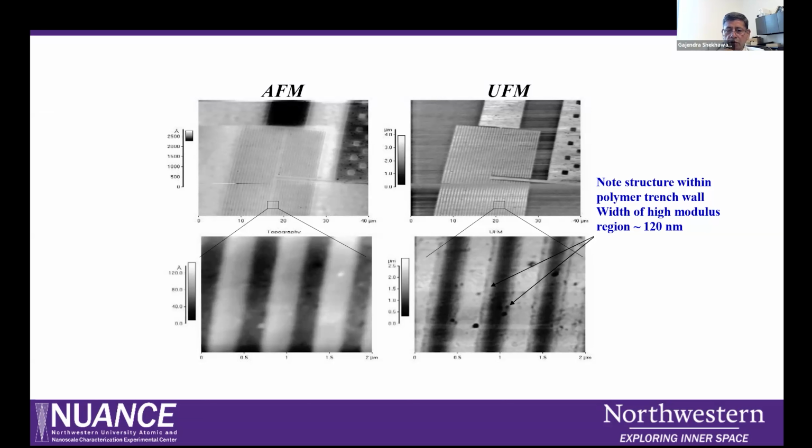So their mechanical contrast is much higher than the polymer, and they appear as a bright contrast. You can also see a lot of holes and voids that come from the polishing effects. So the whole idea is that you can now have a high quality mechanical contrast, so you can study the different effects of polishing or chemical etching on these interconnect test structures.